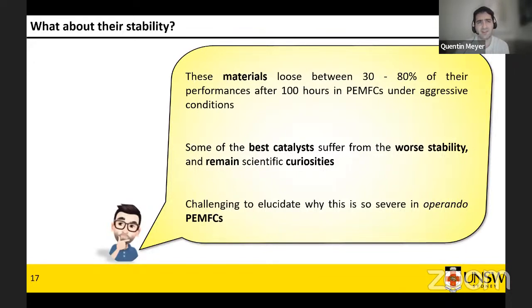Now, the problem with these catalysts is first, they don't behave the same way, but they're also not quite as stable. So the typical durability target for fuel cells with platinum is somewhere between 5,000 and 20,000 hours, losing about 10 or 20% performance. These catalysts can lose between 30 and 80% performance after 100 hours in aggressive environments. What I mean by aggressive is standard conditions that you would run in a real vehicle.